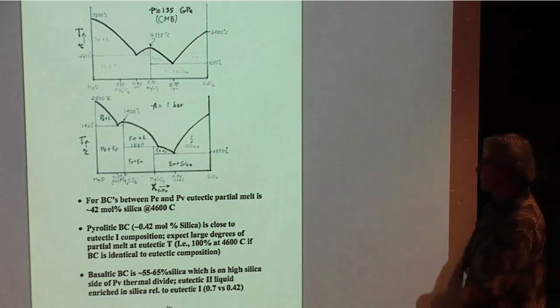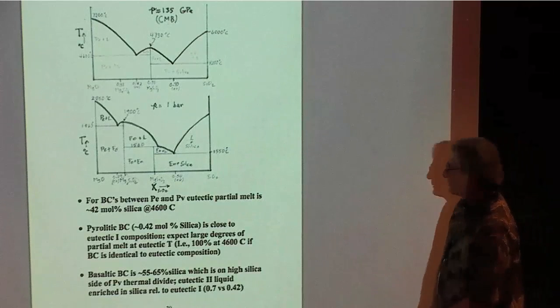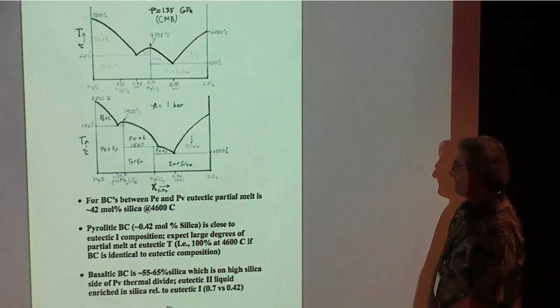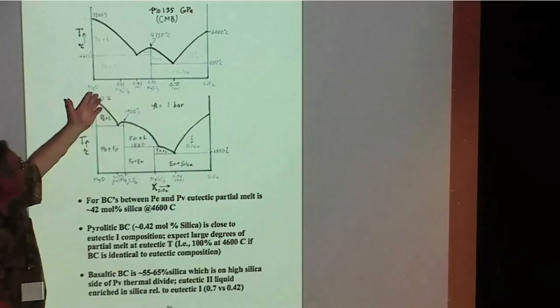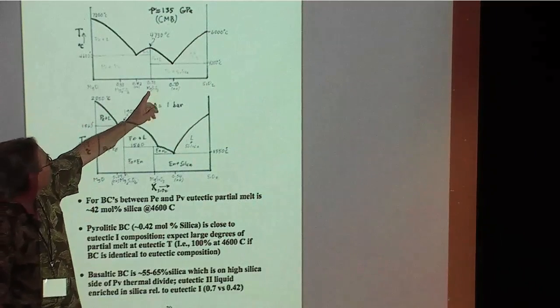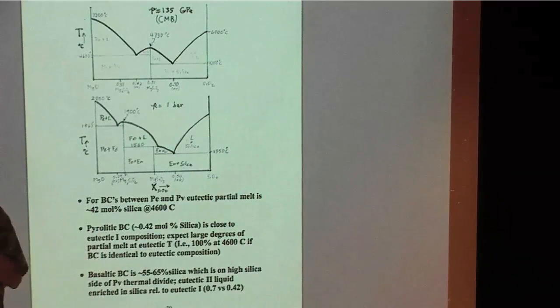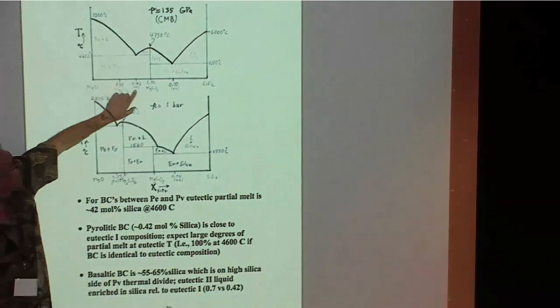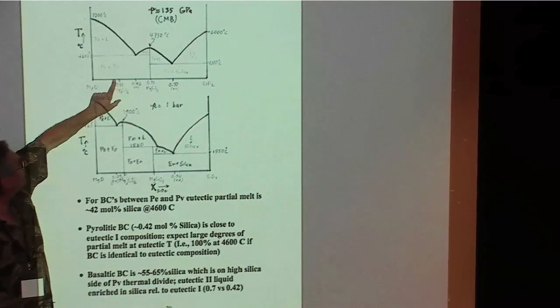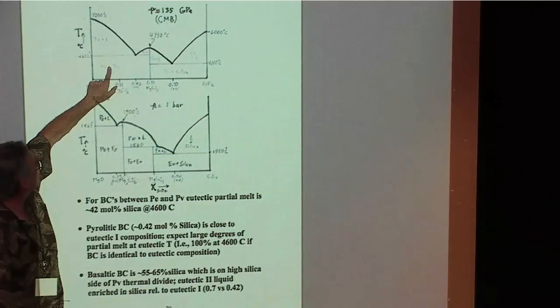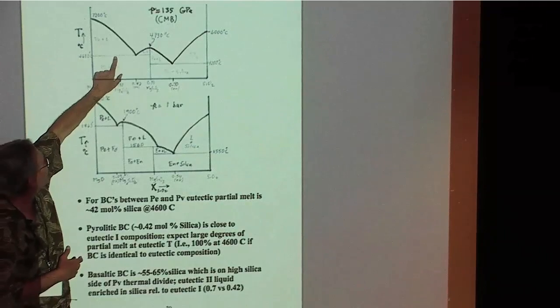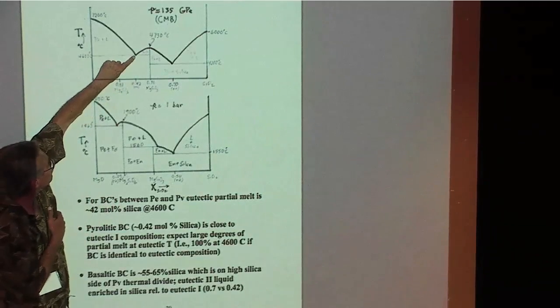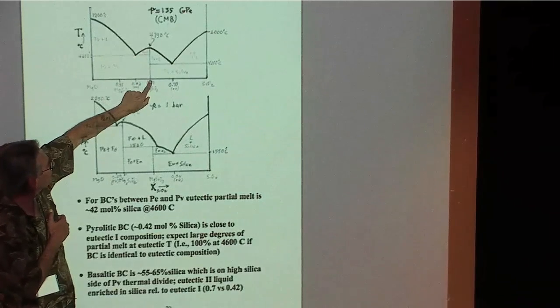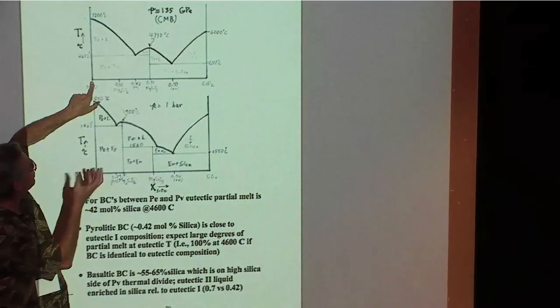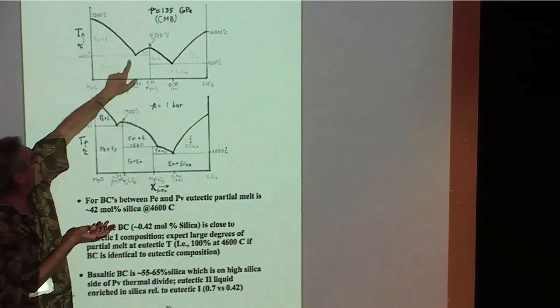Okay, and let's see. Right, so examining this in a little more detail, let's imagine we have a bulk composition, and let's use this as our breakpoint. So remember the lower mantle for peridotite is maybe 70% magnesium perovskite, 30% or 20% MgO. So it's on the left side of this composition, right? A bulk composition here, standard mantle. And so if you had a bulk composition here, and temperatures reach this point, you heated that stuff up, that stuff's going to melt, and its liquid composition would be here, right? So the first liquid you generate, the eutectic liquid, would be at 4600, and it would have this composition.